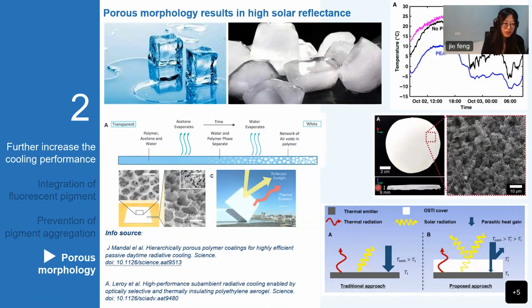The very last approach to increase the solar reflectance was inspired by a very common experience. I believe we all have the experience of seeing water freeze to ice. It usually changes from transparent to white, becoming much more reflective, right? This is because the air previously dissolved in water becomes excluded from the ice during freezing. That brings an idea. What about adding some air voids to the transparent emissive polymer we mentioned previously? Can it be reflective using this approach?